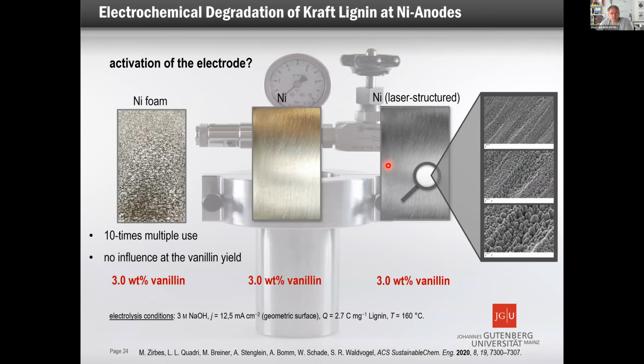The question is, does it make sense at higher temperature to have a foam electrode or a planar or nanostructured one? We did this with a laser. And it turned out at 160 degrees, it makes absolutely no influence anymore because the kinetics are so fast due to the temperature that you don't have to generate a specific electrode system.